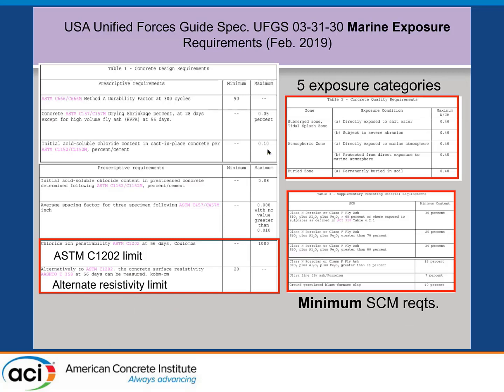As opposed to 318, for example, just the United Facilities Guide Spec has 5 exposure classes just for marine exposures: directly exposed to salt water, subject to severe abrasion, directly exposed to marine atmospheres, protected from direct exposure to marine atmospheres, and buried in soil. So they've got requirements. They have a limit on permeability using the 1202 test of 1,000 coulombs, or they have an alternative bulk resistivity limit. They also have minimum requirements for the amount of SCMs to use to get that permeability. Not maximum levels like 318, but minimum levels that are required, which is quite a different take on things for a marine environment where there are severe problems.